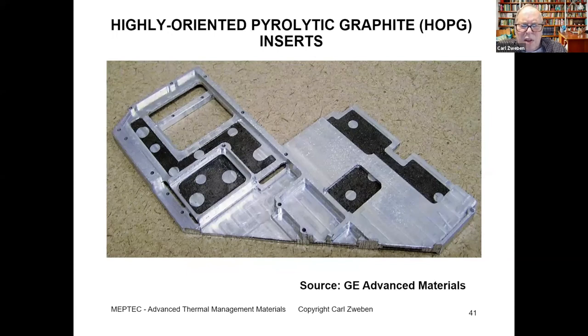I mentioned highly oriented pyrolytic graphite, and here we have a complex aluminum enclosure, where the highly oriented pyrolytic graphite is being inserted in regions where we need heat spreading. With a typical enclosure, we don't necessarily need heat spreading throughout. And so we can selectively reinforce or selectively place our heat spreader material. And we see circular regions of pure aluminum. This is a way to get heat into the highly oriented pyrolytic graphite, which has a low through thickness thermal conductivity. And sometimes these are called heat slugs.